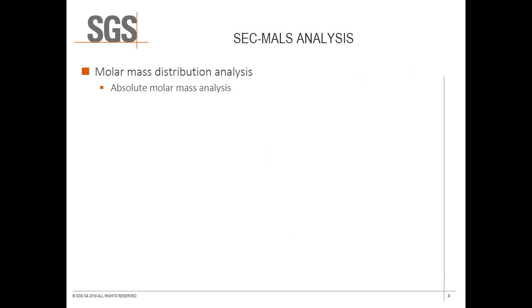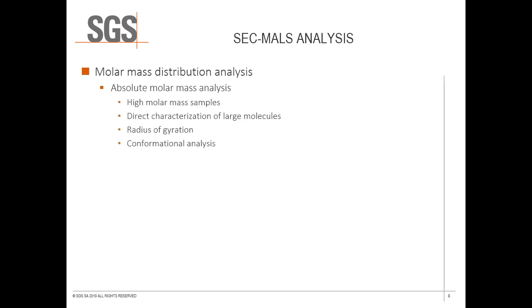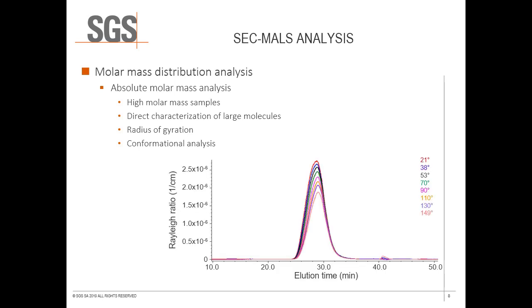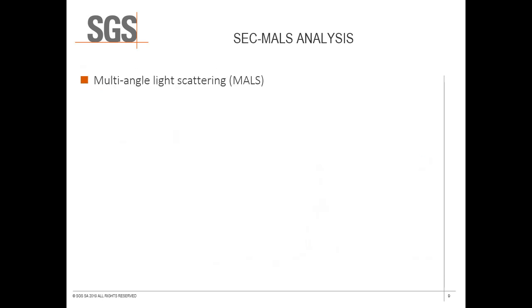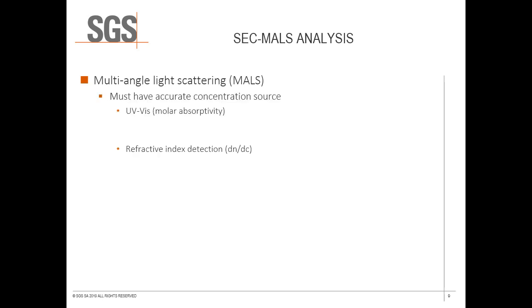The benefit of this method is that you can accurately calculate the actual molar mass of your sample, even if standards are not available. Multi-angle light scattering analysis also allows for the direct characterization of large molecules, nanoparticles, and proteins by considering the differences in the intensity of light scattered at different angles. Certain considerations must be addressed for the proper performance of multi-angle light scattering analysis. Absolute molar mass calculations by light scattering require an accurate concentration source, such as UV-Vis or refractive index detection.